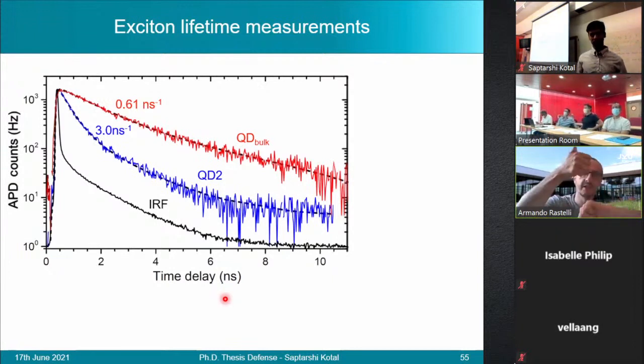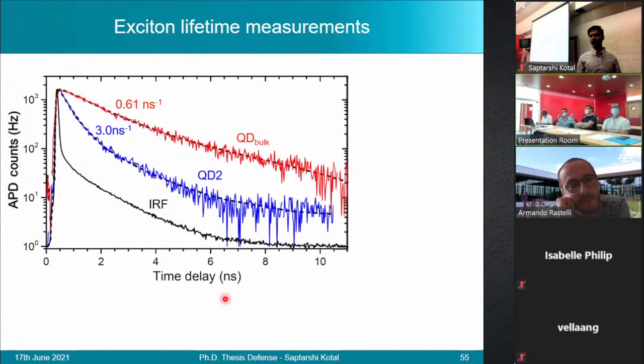So you need essentially a spin flip of what? Of just the electron, or for instance, of a hole, to get this? So what we consider is, we assume that first the radiative rates of the two excitonic states are the same, and we consider that the two dark states also have the same up conversion rate. So we simplify the model into a 3-level problem, and then by assuming that the down conversion and the up conversion are the same rate, we make the calculation to extract the radiative lifetime.